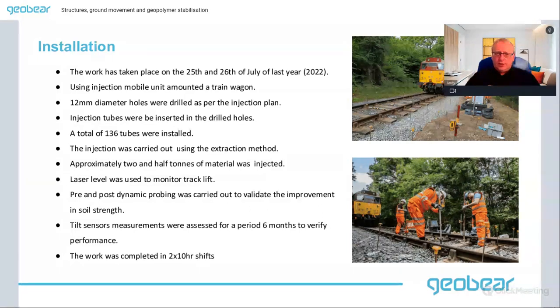We used a total of 136 tubes, and we used what we call an extraction method. We injected roughly 2.5 tons of material into the slope, and we verified the performance on the day using pre and post dynamic probing. We also had tilt sensors on the actual railway track to measure the tilt before and after our treatment. The work was done in 2 10-hour shifts, so it was very quick. The alternative to this solution would essentially be to rebuild the entire embankment, which would have taken months. So this was a very, very quick solution.